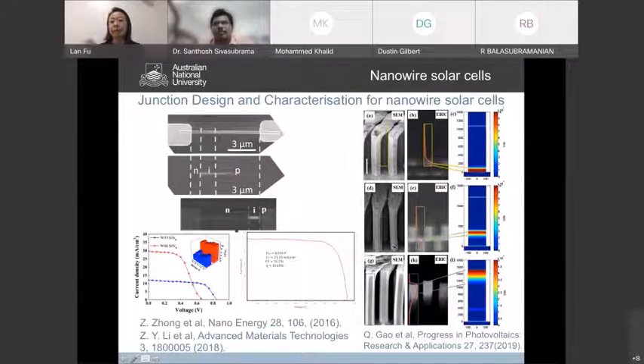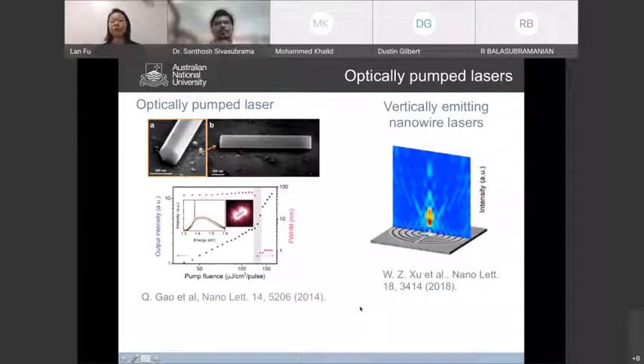And then we're also showing that in the nanowire structure, by putting in doping during the epitaxial process and creating a PN junction, we're able, through some nano characterization, to look at the PN junction built-in electric field in the PIN structure of the nanowire, and thereby understand the electrical properties of the nanowires. By doing that, we can also design different PN junction profiles inside the nanowire structure. As you see here, by changing the doping profile, we are able to shift the built-in electric field across the junction of the nanowire, and then we can design a solar cell with very good efficiency in those nanowires.